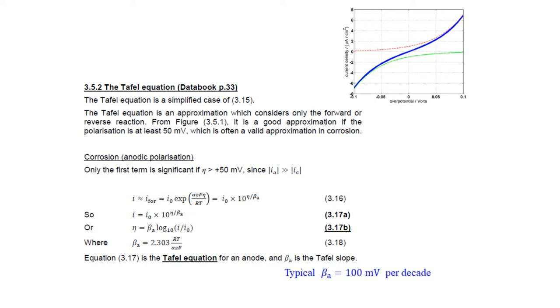So in equations 3.16 to 18, we consider what if we have corrosion, anodic polarization going on. If I've identified that I do have this going on, then only my dissolution of metal, my forward process, is significant. So in equation 3.16, the net current density on the metal surface is just the forward current density, and it's this single term which has an exchange current density times an exponential term with something to do with the polarization in the exponential. So this simplifies to the form of equation 3.17a by grouping the relevant parameters together so that we have current density equal to exchange current density times 10 to the power of polarization over beta a, where beta a is the Tafel slope. You get it by grouping together the constants in the exponential argument of 3.16, and you say the anode Tafel slope is this quantity beta a, given by equation 3.18.